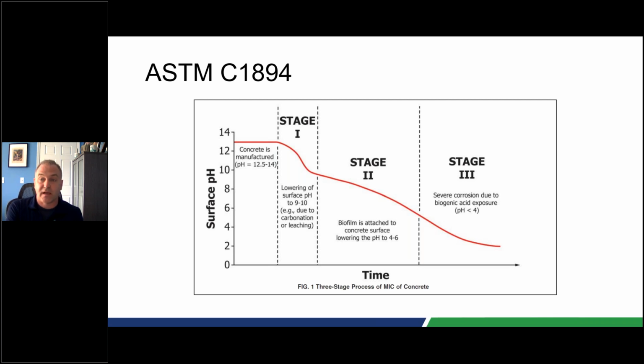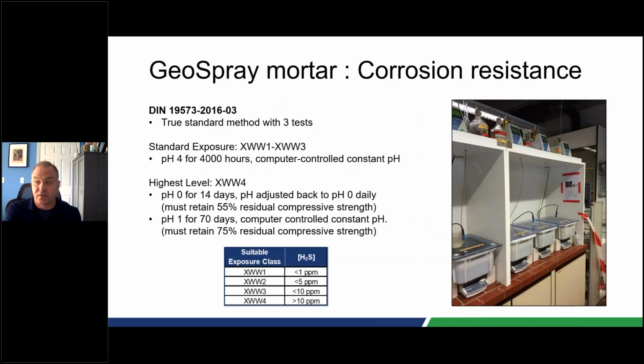These materials are applied in situ, so they start with pHs in the 11s. It says 12 to 14 here. They tend to be a little lower than that, but they can be fairly high. There are multiple stages of basically biogrowth in stage 1 and stage 2 that are lowering the pH of the system to allow the correct microbes that are necessary for corrosion to really occur in stage 3. This can be a process of time and depends on your gas concentration and your sewer conditions. If you have a concrete sewer, this is what's happening in those systems.